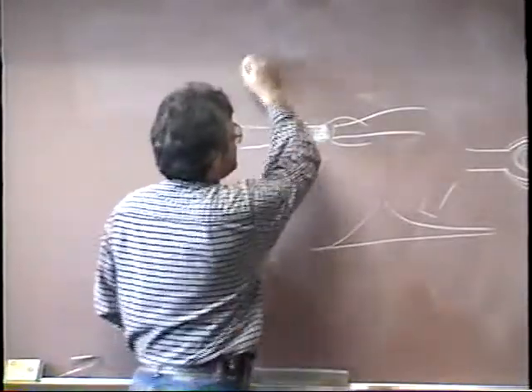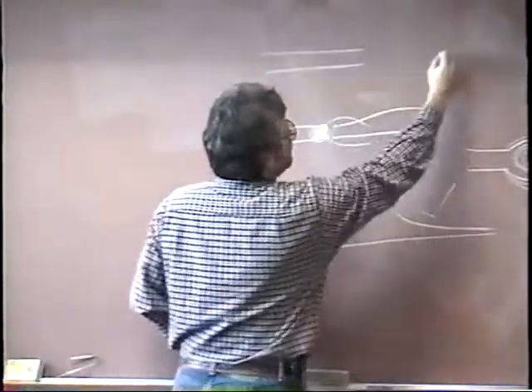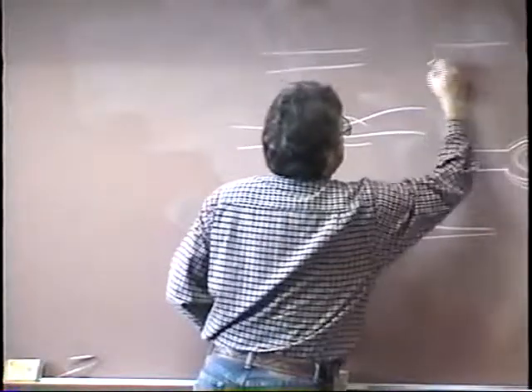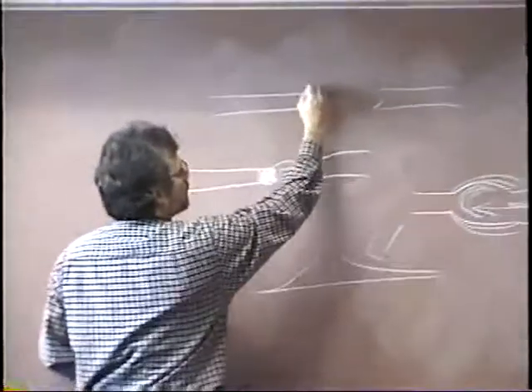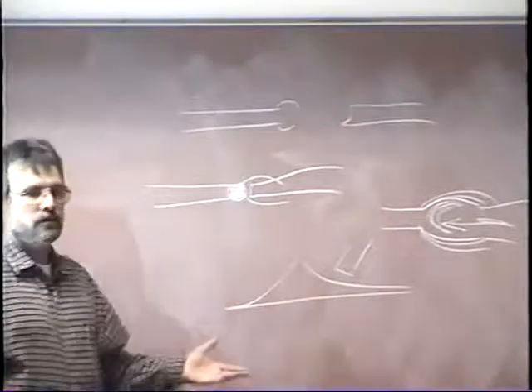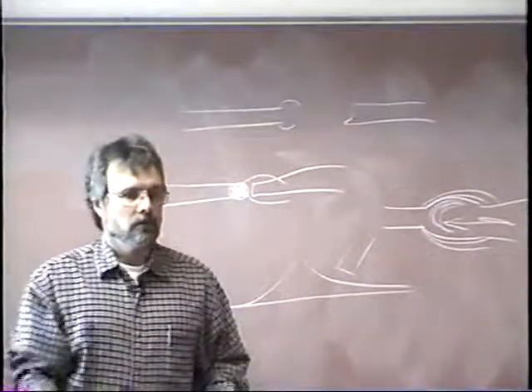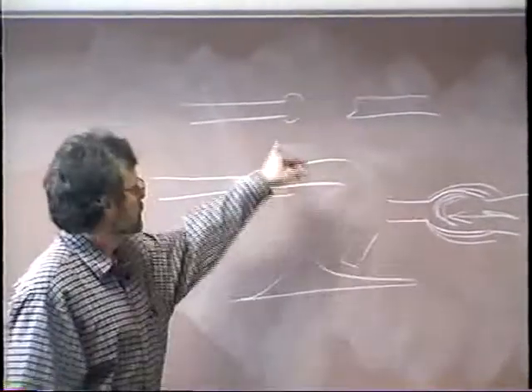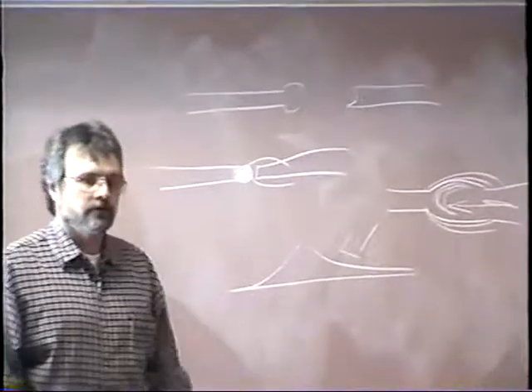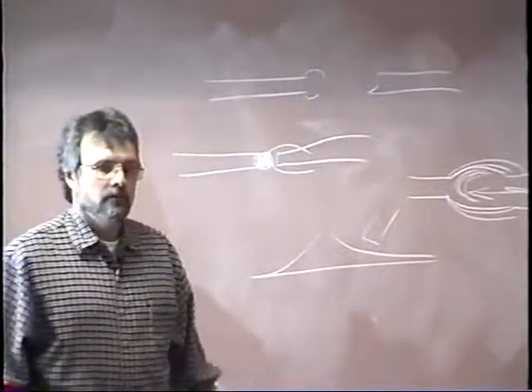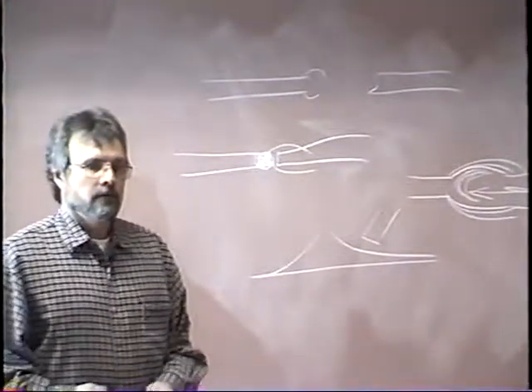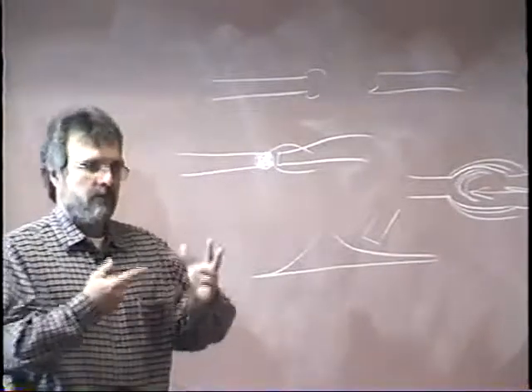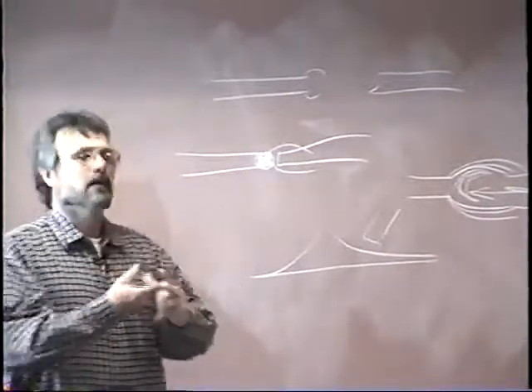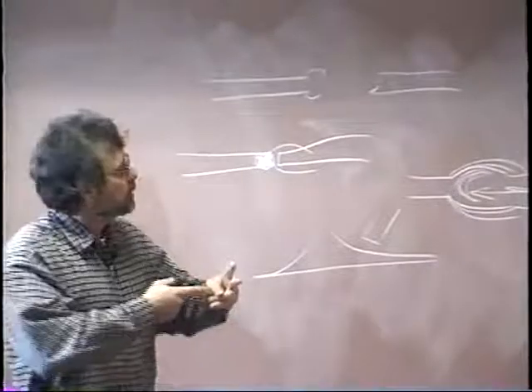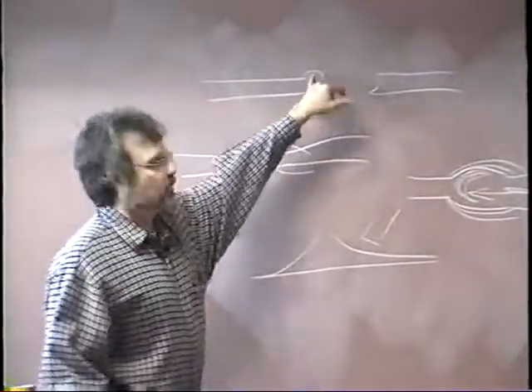That's one way. That's when we're nice and prepped up. But if you're welding across there and your tack's over here and you don't have enough welding rod to reach it, what are you supposed to do? Paul, what are we supposed to do there? If we can't make that tie-in, what do we do with our electrode? Yeah, take it out and start over again. After we punch through. Exactly right. We punch it through and it'll open up your keyhole.